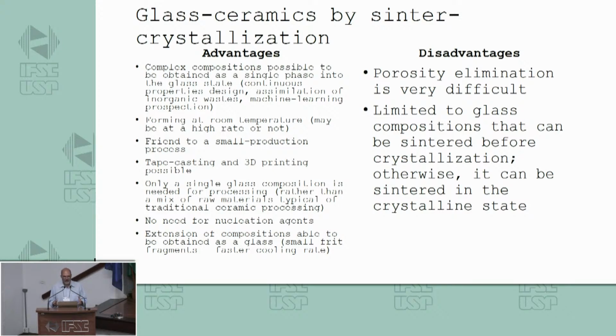For processing, when you are processing, for example, porcelain, you have to mix quartz, feldspar, clay, different kinds of clays. So when you mix that with water to produce a slurry, each of them has a different behavior in solution. And the dispersion is not easy. So you have a heterogeneous system. When you melt all the components into a glass, you have one phase in the system to process. That makes the ceramic process easier. No need for nucleation agents, because all the surfaces are now a place for nucleation.